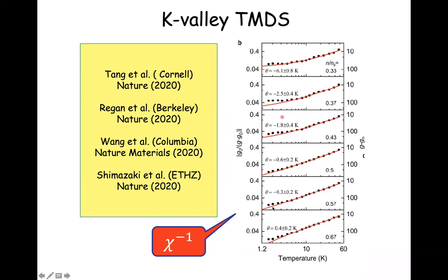The figure on the right is actually an optical measurement of the basically spin susceptibility of a two-dimensional Hubbard model as a function of the number of electrons per period of the crystal. And by doing similar experiments, people have demonstrated that lots of different correlated insulator states occur in this system, some not entirely expected.